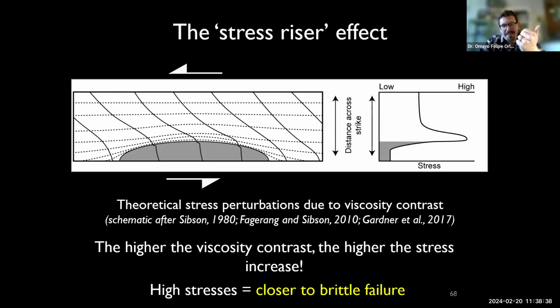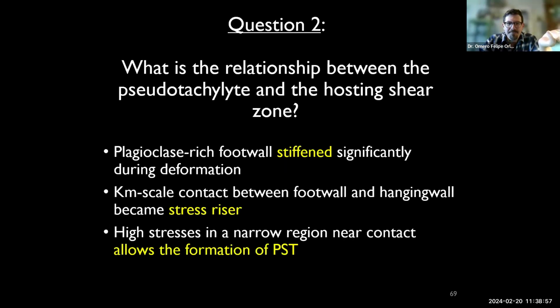So that ends up being our best explanation for why you end up with super high stresses right on the domain contact between the plagioclase-rich half of the shear zone and the quartz-rich half of the shear zone, and maybe why you get your pseudotachylites there. Because if your stresses are high enough, rock's going to break, right? Or it's way more likely to break. So this is summarizing all of that.